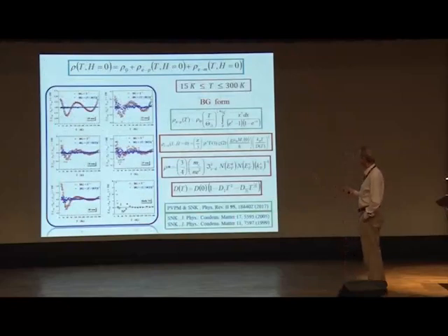Now you can see this. Now we stick to the Bloch-Grüneisen case because we saw in the earlier slide, with just the added T square term, Bloch-Grüneisen was giving a better fit than the Bloch-Wilson case. That means the intra-band scattering was much more prominent than the interband scattering.